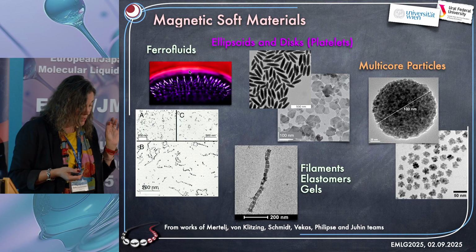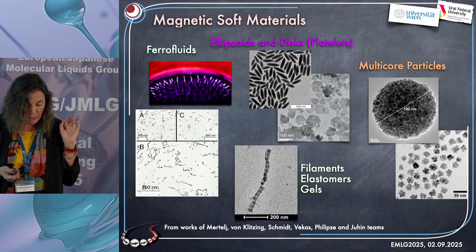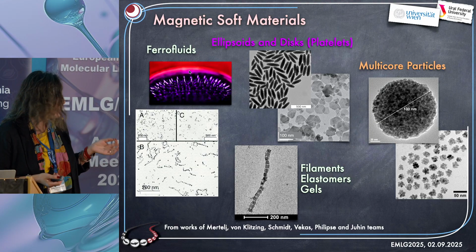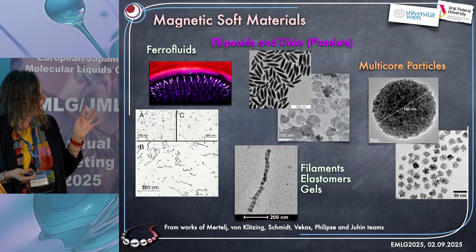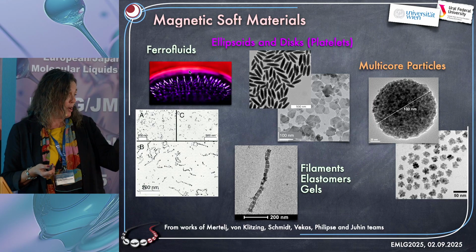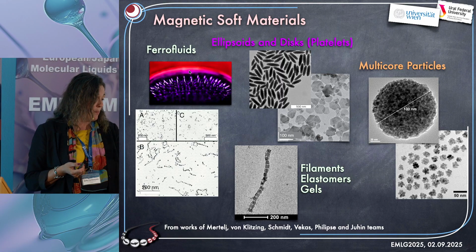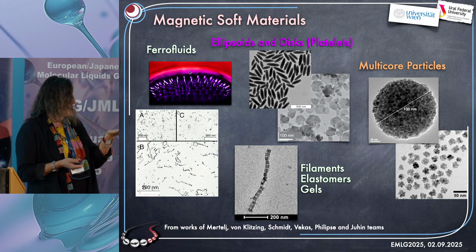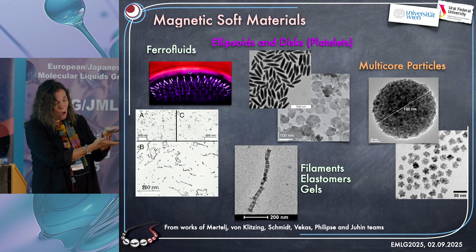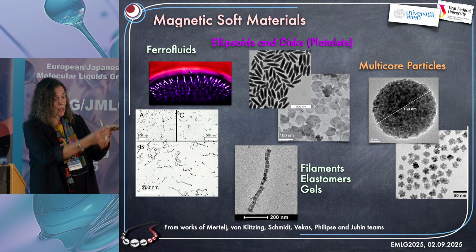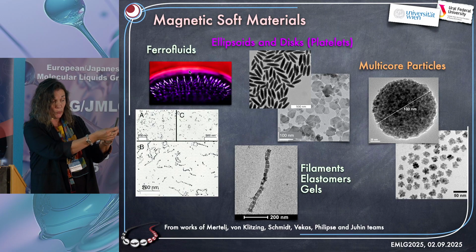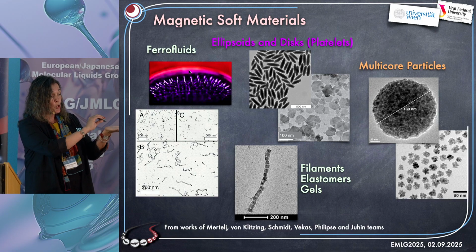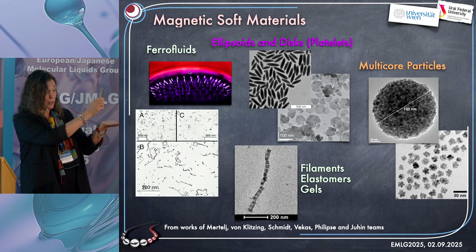The story is that these are magnetic nanoparticles, approximately between 10 and 50 nanometers in diameter, suspended in a liquid carrier. If you put such a magnetic fluid on a substrate in a petri dish and put a magnet from below, you have magnetic field lines going through the fluid, magnetic nanoparticles trying to follow the field lines, and the surface tension of the fluid pulling them back.